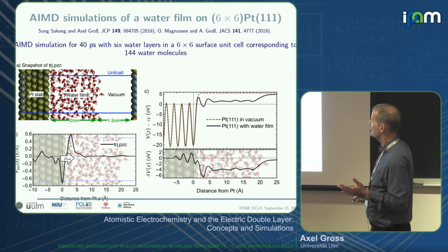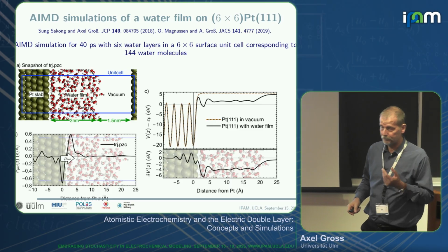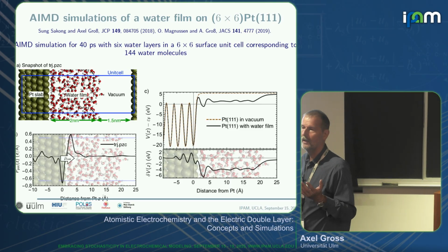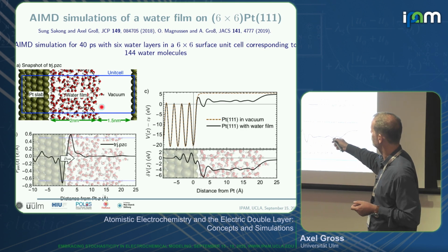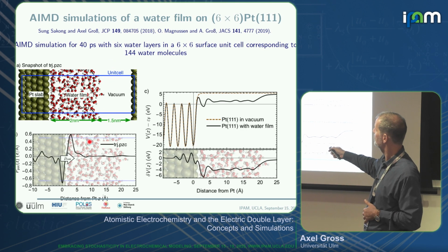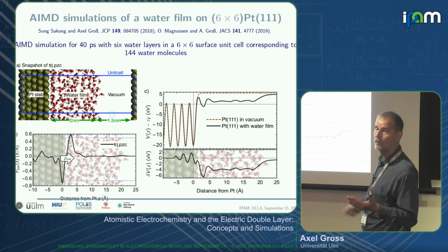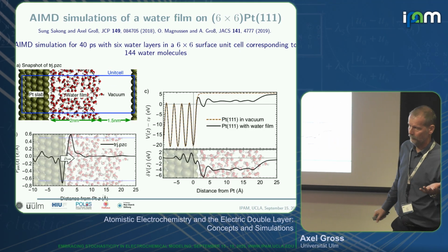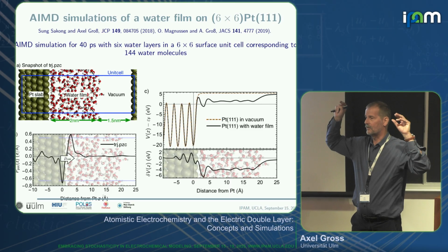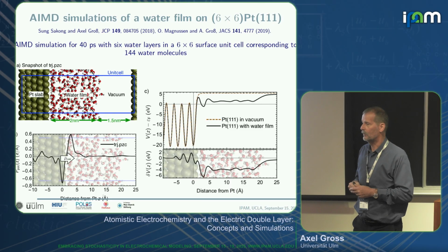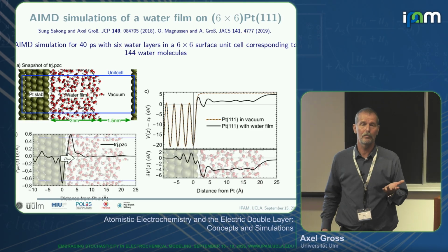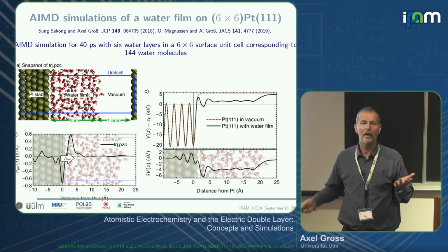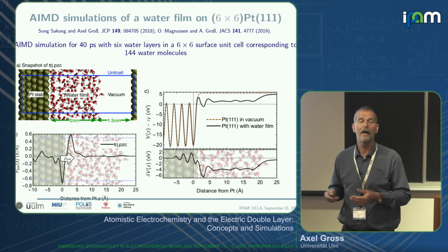And then also the question, how did we change the electrode potential? We have here a vacuum cell, so we can measure the unit cell work function, and we use the concept of Trasatti. The experts among you know the discussion about the 4.44 eV or so, but this is exactly what we use. And how do we change the potential? We changed it by adding or taking away hydrogen atoms.